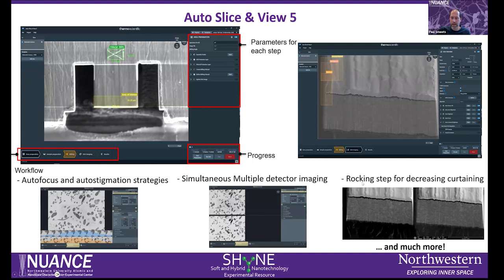There are other things available in the software as well. For example, you can do a rocking polish. A rocking polish is basically, after you remove a slice of material, if you see that the cross section is not good and there's a lot of curtaining, you can decide to build in a rocking step. You tilt the sample at a specific angle and rotate it so that the ion beam impinges on your sample in a different direction.